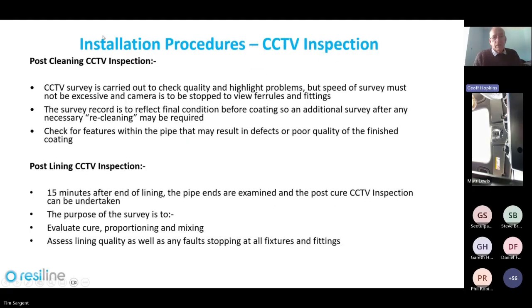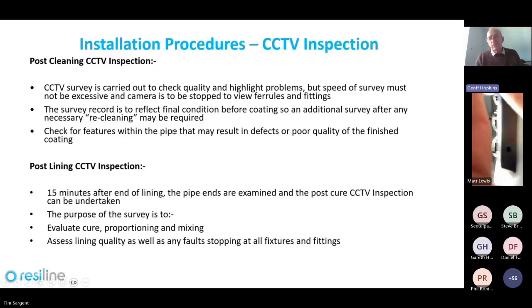And we carry out the CCTV survey to check the quality of the cleaning and highlight any problems. Speed on the clean water side, we go a bit faster than the sewer lining guys. We go up to 10 meters a minute as opposed to their 7. But generally you would stop and view ferrules and fittings. And as I said, it's to check the final condition of the pipe before you line it. And also you might be able to identify some defects in the pipe that could affect the quality of the finished lining.